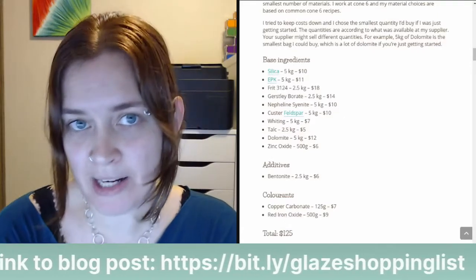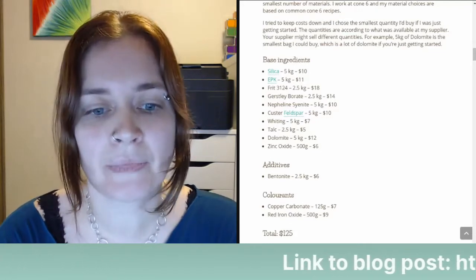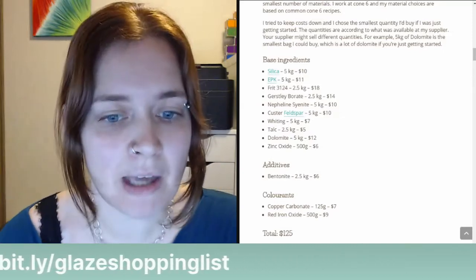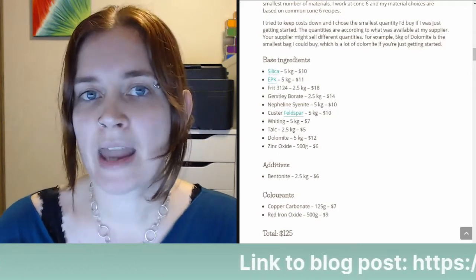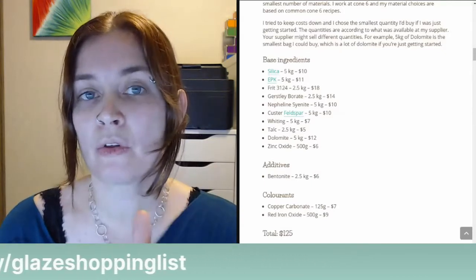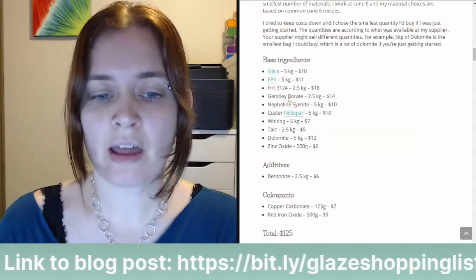Whiting is calcium carbonate — it might not be called whiting where you come from. That's one of our alkaline earth fluxes. Calcium is an alkaline earth flux, whereas sodium and potassium are alkaline metal fluxes, and they perform different roles in the melting of our glazes. We've got whiting for calcium, talc which is a magnesium silicate, and then dolomite, which is a combination of calcium and magnesium. Calcium and magnesium are both alkaline earth fluxes — those are the secondary fluxes in a glaze recipe. And then also zinc oxide, which is another secondary flux.